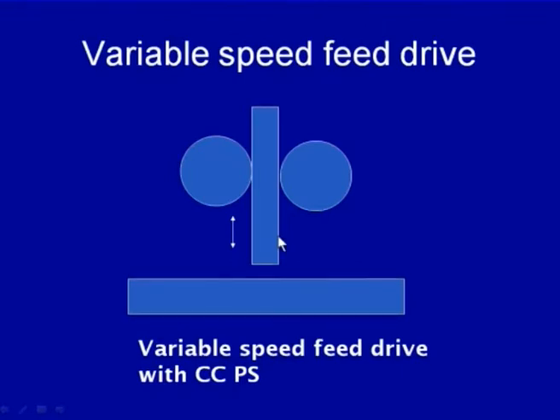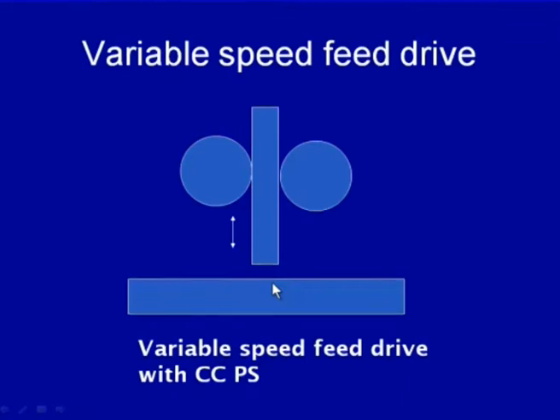Under these conditions, the constant current type of power source is used, so that the heat generation rate is constant, and a constant heat generation rate means the melting rate will also be constant. If due to any reason a fluctuation takes place, then the arc gap will either increase or decrease. To take care of these fluctuations in arc length causing the change in arc gap, this will change the arc voltage. This change in arc voltage is used as an input for changing the current value being used for driving the motors of these feed rollers.